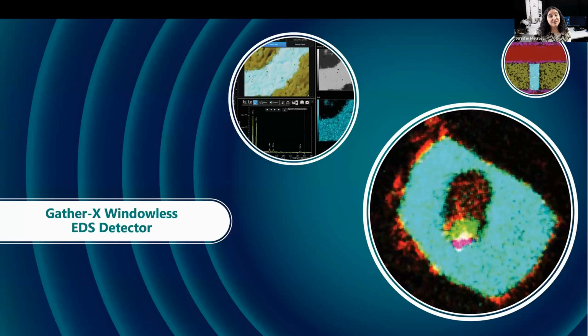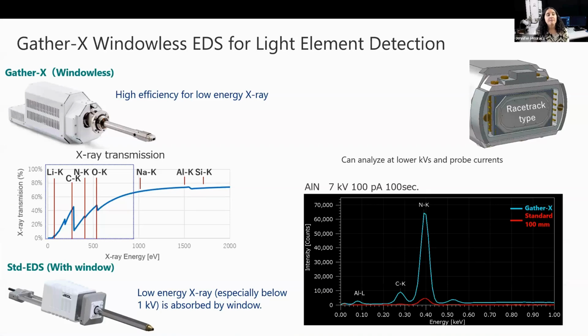Okay, so for the remainder of the talk, I'll be showing data gathered using our advanced JEOL X-ray detectors on the ultra-high resolution field emission SEM. I'll start by showing data from our Gather-X Windowless EDS detector. This detector is 100 millimeters squared and has a racetrack design. It can be used at any kV, but is especially sensitive for detecting low energy X-rays down to 50 eV.